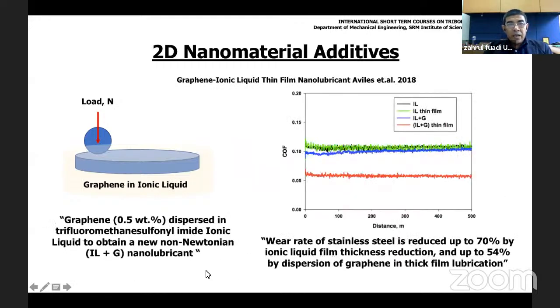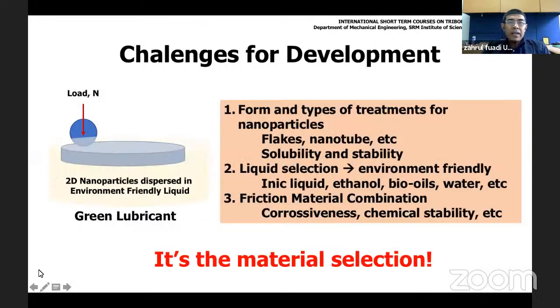And this one shows that graphene is dispersed in ionic liquid. These researchers here use this ionic liquid and achieve lower friction compared to the ionic liquid that has no graphene dispersed. And here, the wear rate of stainless steel can be reduced by up to 70% by the ionic liquid film, and then 54% by dispersion of graphene in the lubricant. So, what is the challenge for the future?